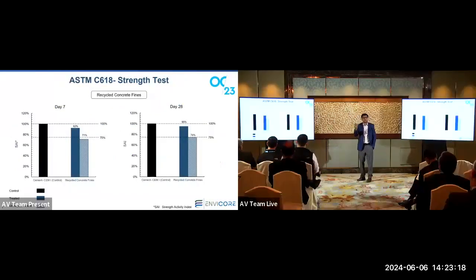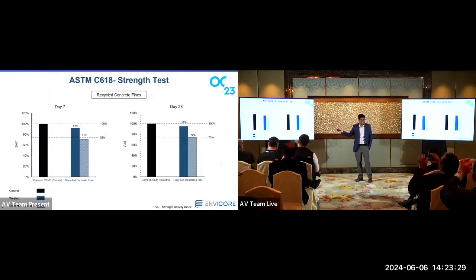Now, based on the 12 samples, we categorize these different samples into different categories. The first category is recycled concrete fines. And there are a couple of parameters that we're going to talk about. Strength activity index, pretty common in the cement industry, is basically the compressive strength of your material. That means your blend of 80% cement, 20% SCM, divided by your 100% control cement.